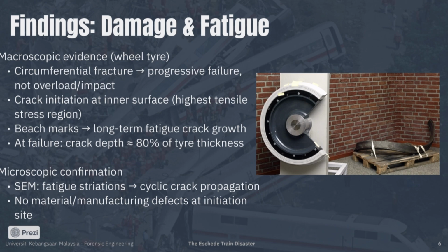Our findings show the wheel tire failed by fatigue, not by a sudden overload or impact. The fracture is circumferential and indicates progressive damage accumulation. The crack initiated at the inner surface of the wheel tire, which is consistent with the region of high tensile stresses during high-speed operation. Beach marks on the fracture surface show long-term crack growth over time. At the point of final failure, the crack had reached roughly 80% of the tire thickness, leaving only a small remaining ligament that could no longer carry the operational loads.